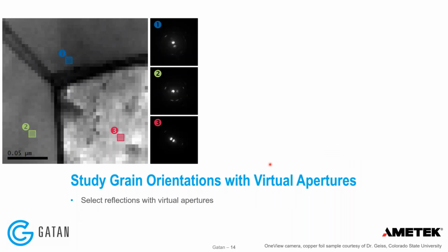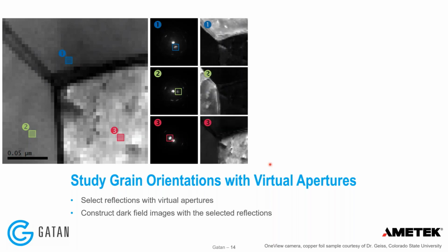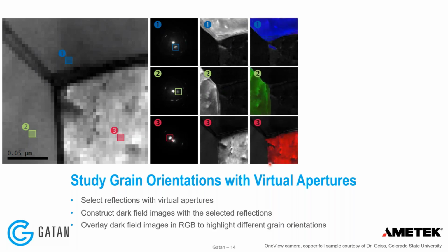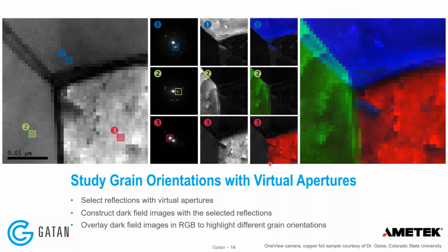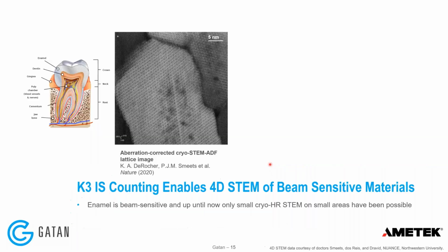This is a copper specimen at the grain boundary. I have extracted diffraction images from each of the grains, and then we use specific reflections in each of the diffraction images to generate the dark field images, and then you can color those virtual dark field images and get a color map of this grain boundary in the copper sample.